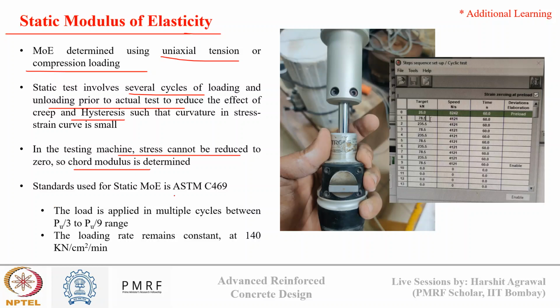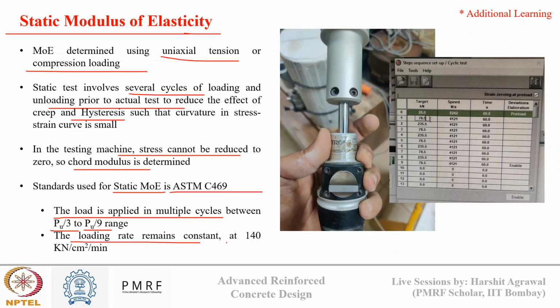You see there are ASTM standards present for static MOE testing, and the load is applied in the range of PU by 3 to PU by 9. Only at a very small stress level we apply the load, so that there is no permanent strain in the concrete. And we keep a very constant loading rate. So this is an LVDT. This is basically attached on the surface of the concrete.